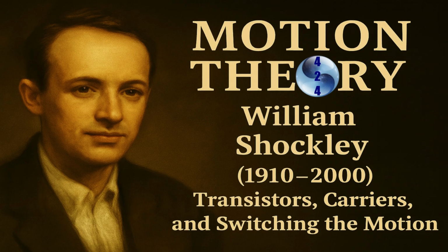Precisely. The stability of that gap is absolutely everything. If EG were too small, thermal energy, kT, just heat, would constantly be kicking electrons across the gap. The semiconductor would become an unstable conductor, no reliable switching. Right, it would just be noise. Just noise. But if EG were too large, it would be an insulator, and no amount of voltage could really create the flow you need.